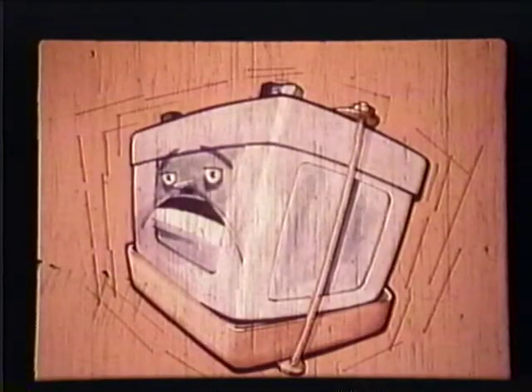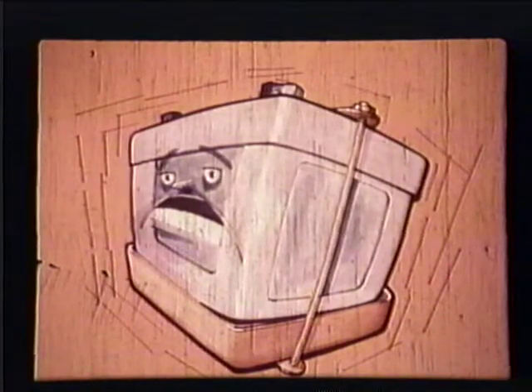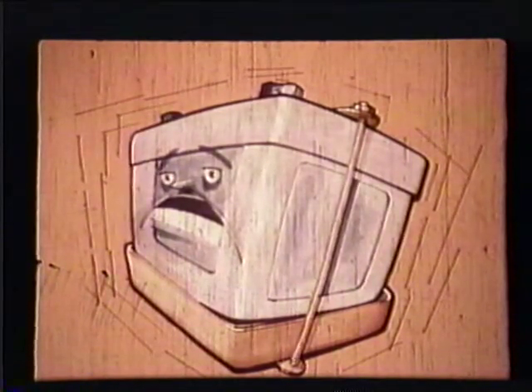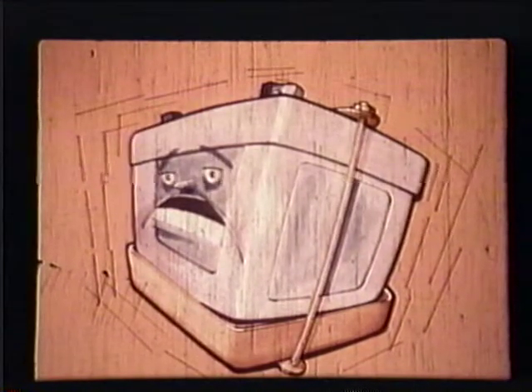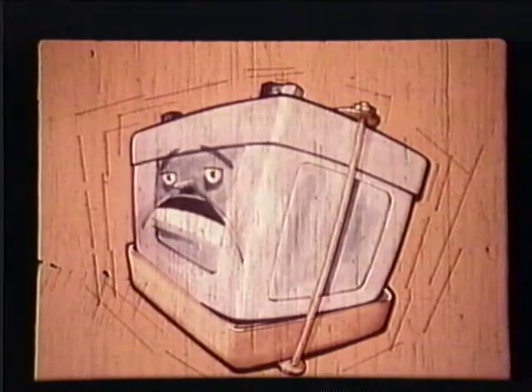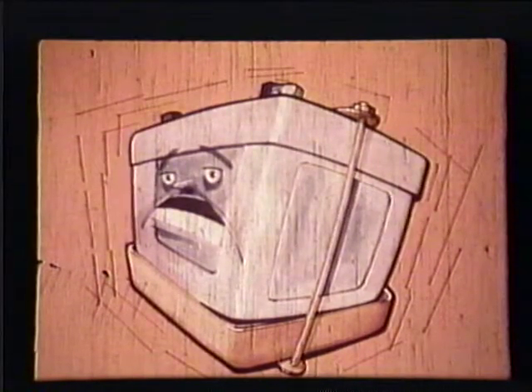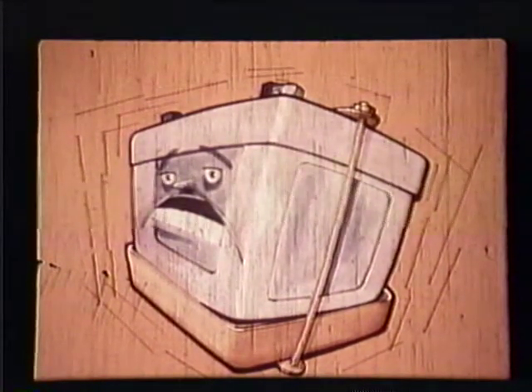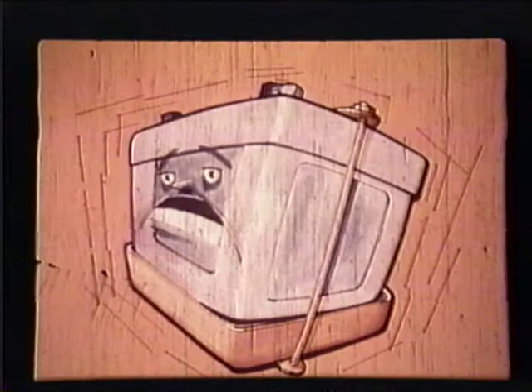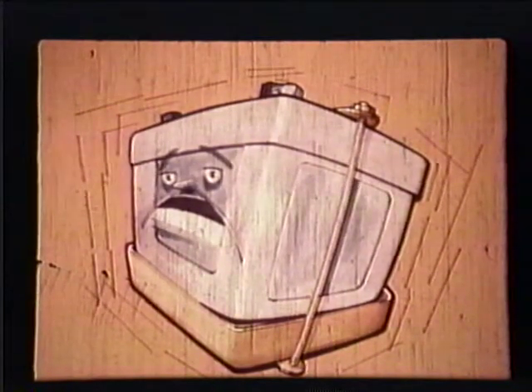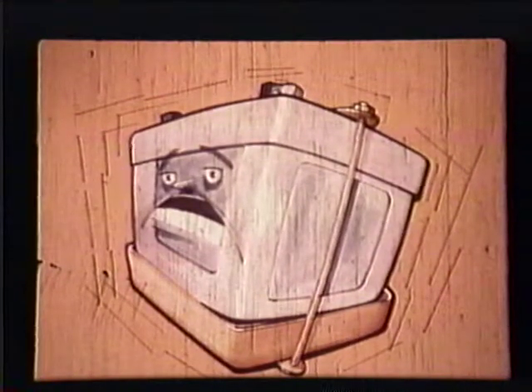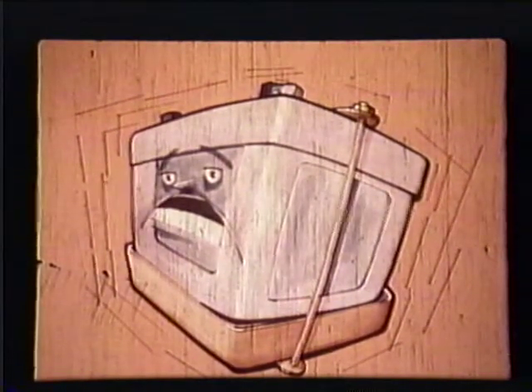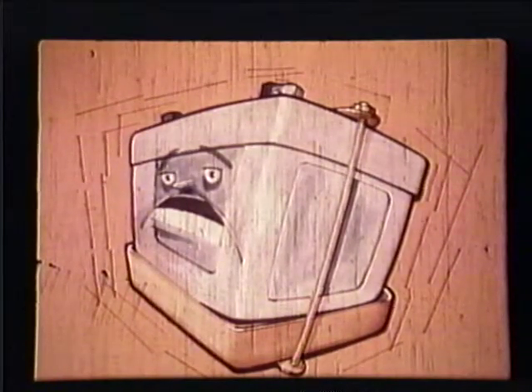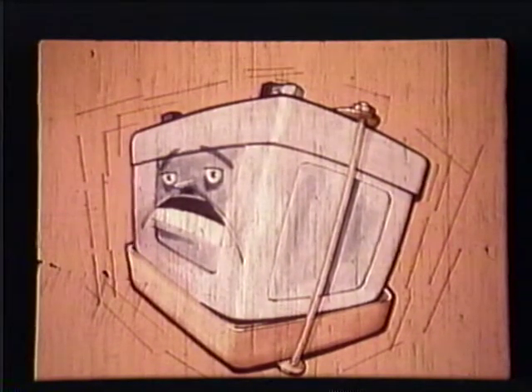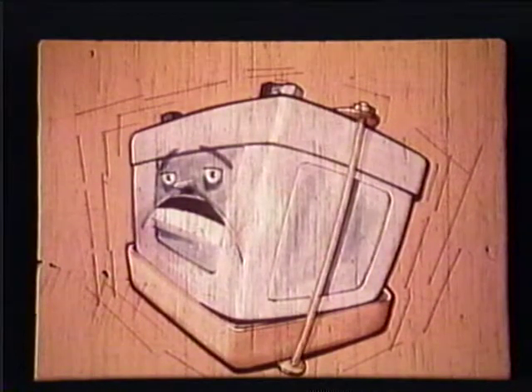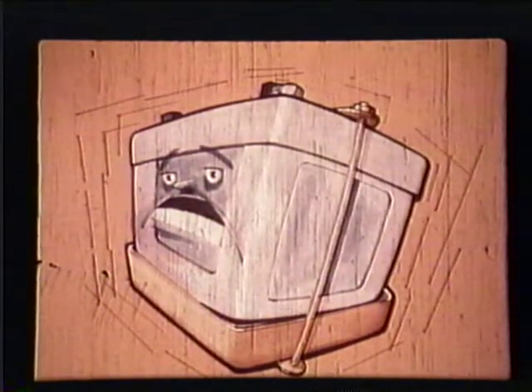Damaging vibration can occur on some applications, and high-speed cameras can show that the battery is actually vibrating or being shaken severely. The battery case may crack, and the plates and separators may be damaged to the point where the battery may fail completely. Proper battery selection and secure hold-downs for the application are essential for satisfactory life. Improved mounting locations and proper battery capacity recommendations for heavy-duty diesel trucks are further covered by the regular Common Carrier Conference recommended practices.